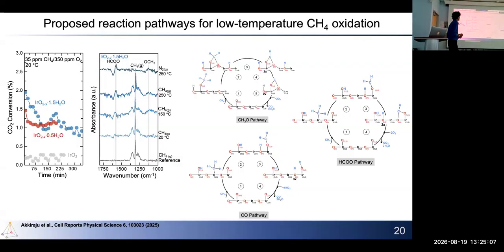Based on this, we were able to identify the active species for why iridium is so good with methane conversion. And then, I won't go into the details, but we are also able to propose different pathways based on the different reaction intermediates that we saw, both in the XPS experiments as well as lab scale IR spectroscopy.